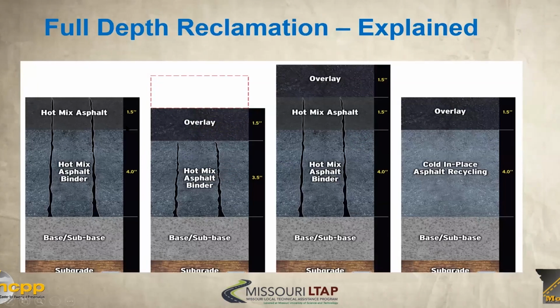Full depth reclamation explained. So if you look at this, this kind of gives you a schematic of what we're talking about, FDR versus CIR and some of the things that we look at. So if you look at the base and sub-base, we want to know what's going on down here in the base, sub-base, subgrade, and are the cracks coming from there or not? So that's why oftentimes you'll see the coring be the critical component here. If it's this kind of situation, then we're going to feel pretty comfortable that cold in place might be a good option. So you can see over here, cold in place. However, if we saw cracking down into the base, then we'd have to kick this out as a CIR candidate and look more at full depth reclamation.